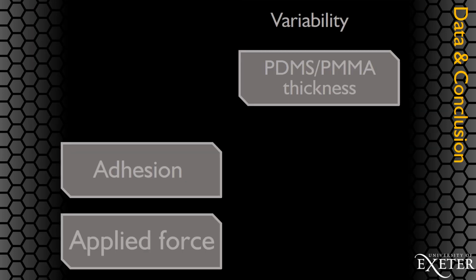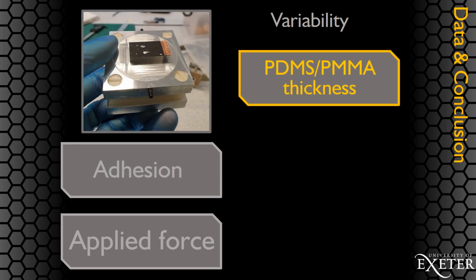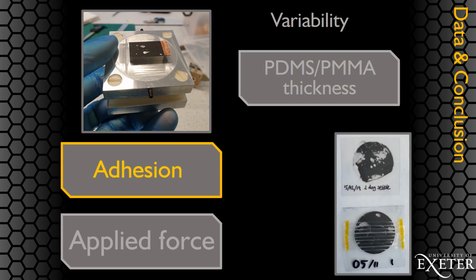Producing these nanogenerators involves taking into account many variables. One often overlooked factor in the literature is the thickness of the triboelectric material used. Unknown thicknesses can alter the results dramatically, making reproducibility difficult. The thickness of our PDMS could not be determined due to the difficulty in drop casting such a viscous fluid. The graphene adhesion to PET and PP fibers was also prone to variability, often having no discernible way of telling why a transfer was successful or not.